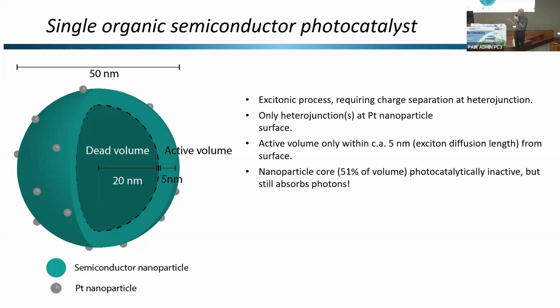But also, with a typical organic semiconductor, it's quite hard to make nanoparticles less than about 50 nanometers. So if you have a 50 nanometer nanoparticle, the typical maximum exciton diffusion length within an organic semiconductor is around 5 to 10 nanometers. So what that means is that any excitons that you're forming in the middle of this nanoparticle, they're never getting out. They're never generating free charges. So what happens is they'll just geminately recombine.